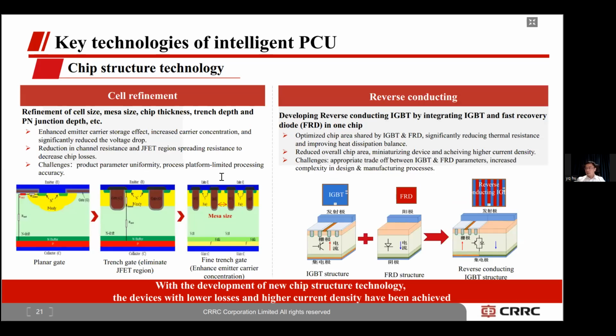With the development of new chip structure technology, devices with lower losses and higher current density were made possible. Refinement of cell size, mesa size, chip thickness, trench depth, PN junction depth, and so on was then achieved. Enhanced emitter carrier storage effects increased carrier concentration and significantly reduced the voltage drop. Reduction in channel resistance and JFET region spreading resistance decreased chip losses. However, we are still facing challenges such as product parameter uniformity and the limited processing accuracy of the process platform.